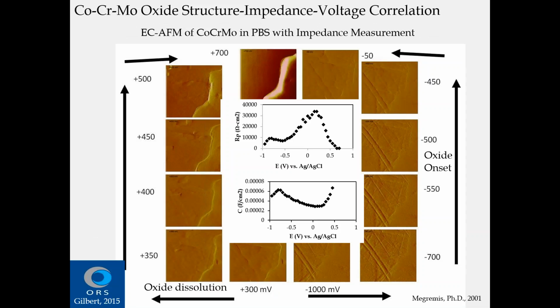We can also look at cobalt-chromium alloys with atomic force microscope methods, electrochemical AFM methods. And again, just to show you the nature of the oxide films, I have a series of AFM images running around the right side from -1 volt up to -50 millivolts. If you look carefully between -500 and -550, you can see a distinct change in the scratches here that are on that metal surface. As you keep going up, those scratches fill in. That's the oxide showing up and growing and filling in. By -50, those scratches are almost completely filled in.